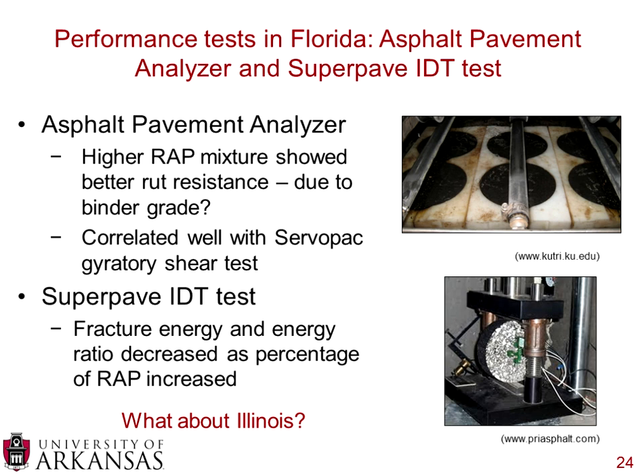They ran 2 performance tests. They ran the asphalt pavement analyzer, which is a rutting test, and they also used the SuperPave IDT, which is a cracking test. For the asphalt pavement analyzer, they showed that the higher RAP mixture showed better rut resistance, but they weren't sure if that was due to including the RAP or the fact that they used a different binder grade. So there were kind of 2 factors there that they couldn't separate. And they found that the APA measurements correlated well with the Servopac gyratory shear test results.